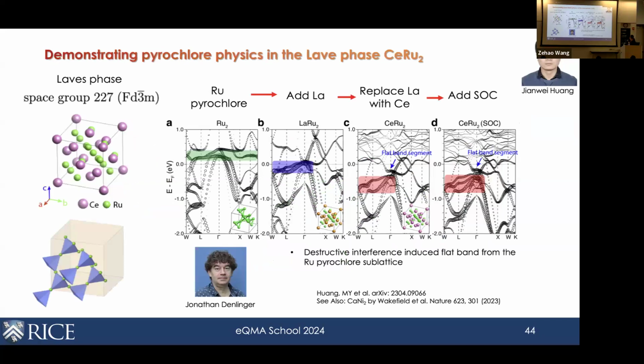We wanted to see how the pyrochlore electronic structure is preserved in this compound, so we did the following exercise. These are calculations by Jonathan Denlinger. First, we start with the pyrochlore lattice. He calculated the density functional theory calculation for just the pyrochlore sublattice, and these are the topological flat bands associated with it. The next step is to put in these pink atoms. In this case, he first put in the lanthanum. You can see that there's some slope, a bandwidth gained by these states, and they're also pushed down.